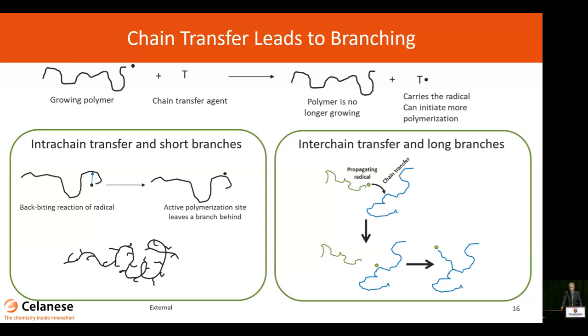The second form of branching that occurs is long chain branching, and this comes from interchain transfer. Essentially, if you have a meaningful concentration of dissolved polymer in the polymerization medium, in the same solution with growing radicals of polymer, you can get transfer from one polymer to another, and that introduces a place to start polymerization at some point along the polymer backbone. As the polymer grows off of that, you'll create a long chain branching architecture. So we have to concern ourselves with both of these things.